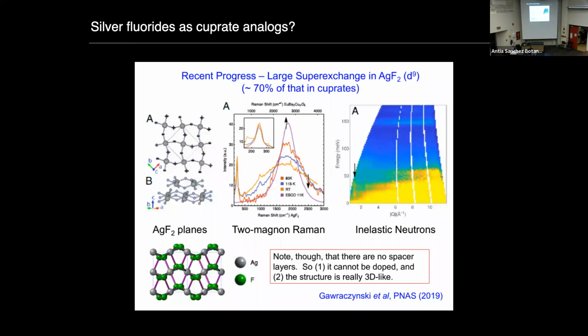But before I do that, I just wanted to mention that concerning the silver route, there has been some progress in the past 2 or 3 years, actually looking at silver fluorides instead, rather than oxides. So what people have been looking into is this material here, silver difluoride. In this case, silver is actually happy being in a 2+ oxidation state. And what has been found is that in this system, one can actually get a large superexchange as well, somewhere around 70% of what you get in the cuprates.